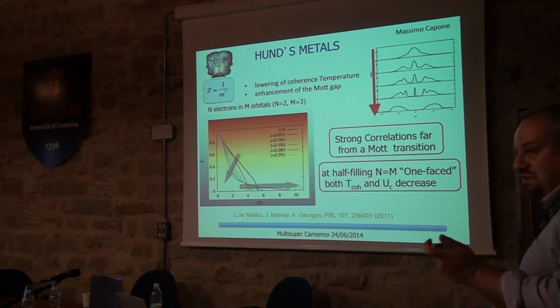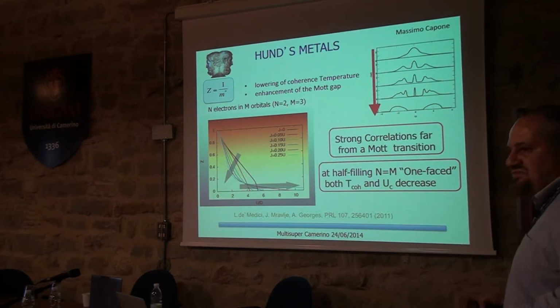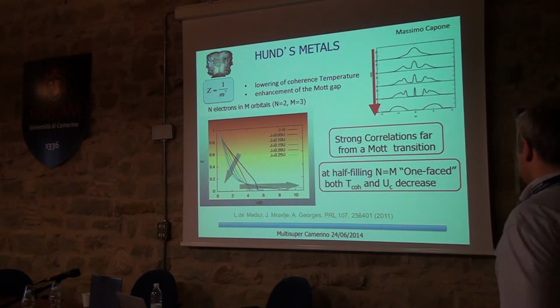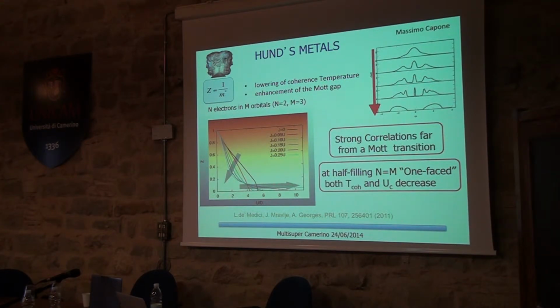The features at the Fermi level are very narrow, but the Mott transition is far, far away. This only happens when the number of electrons is different from the number of orbitals, as it happens for the iron-based superconductors. In the more standard case of half-filling, which is the one more favorable for a Mott transition, this doesn't happen. You still have a one-faced thing, which actually drops very fast.